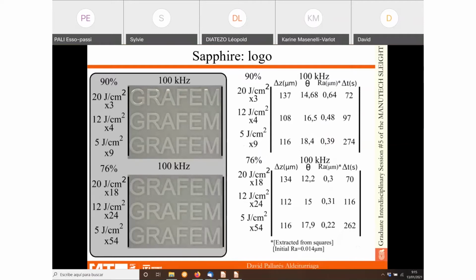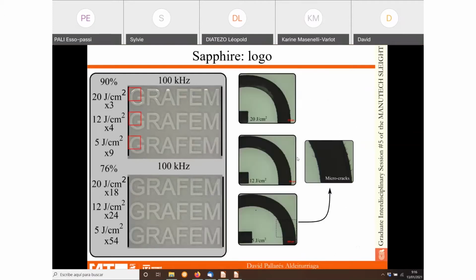Okay, sapphire. What happens with sapphire now in comparison with PEEK? Well, first thing, the scan number increases. We require more scans, thus it takes more time. Also, we see that at high fluence and high overlap ratio, we have some defects, some debris here. If we highlight with the microscope, we can see it here, but we see another thing at all of these fluences, which is these micro cracks here.